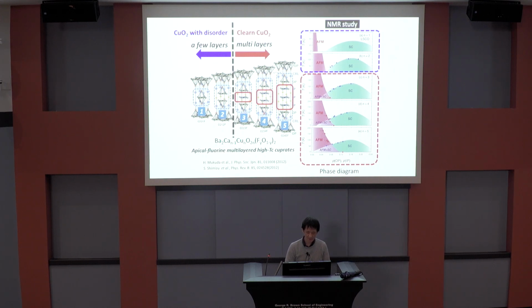The phase diagram of these two regions is also different. In the multi-layer system, the antiferro state and superconducting dome are extended to a wider doping region. Then there is an overlapped state, which is very different from the very famous phase diagram of cuprate constructed from the single and double layered cuprate.